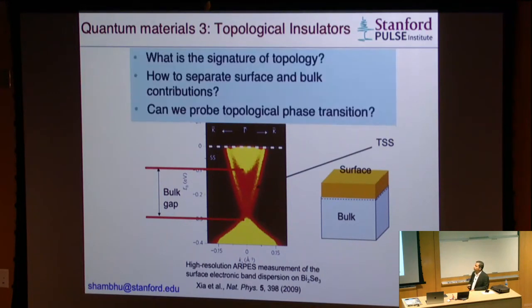So in our spectroscopic approach, we wanted to find out what is the signature of this topology in our high harmonic spectrum. How do we separate the contributions between the surface and bulk? Because the optical laser goes through both the surface and bulk, right? So we want to be able to separate this, and then eventually, if we find those signatures, we will have a way to probe a phase transition in materials, topological phase transitions, when materials go from a non-trivial topological phase to some trivial topological phase.